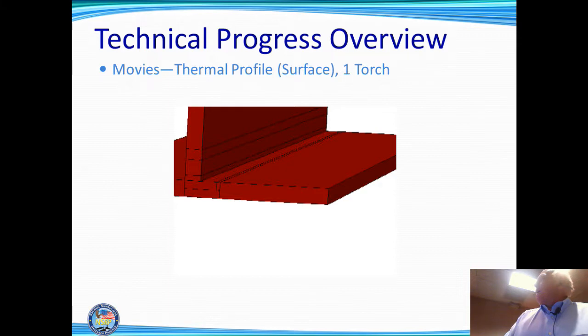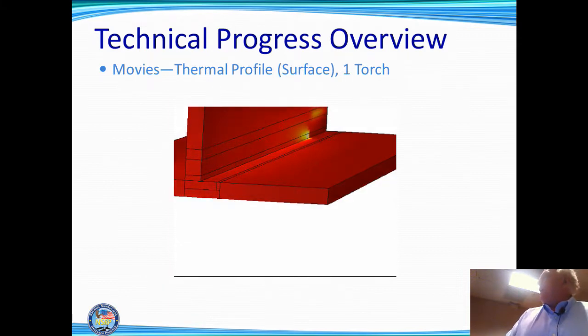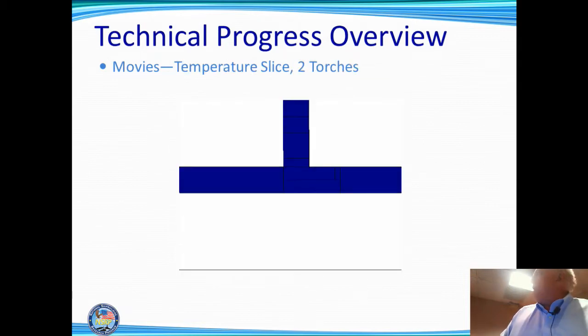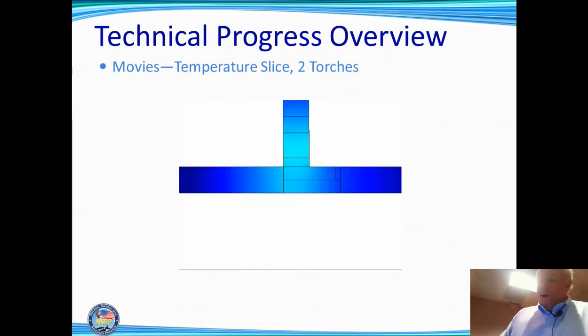So I brought along a couple of these little videos so you can see, and I'll go back with this one. We actually heat the material up on the discontinuous member a little bit here. If the T-fillet's like this, we actually heat it up there to get the right heat flow to reduce the distortion. So you watch again, you can see the induction and then the arc down on the bottom. And I've got a little bit better 3D model, so you'll see the heat in cross section. I'll go back and run that again.